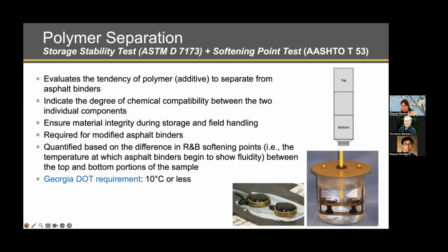So the test is pretty simple. As you can see here on this illustration, we have the blend of the asphalt binder with the polymer or the additive, in this case, graphene. We have the materials stored in a cigar tube, that is an aluminum tube, as you can see in this picture. And after conditioning at cold and room temperatures, we separate the top and the bottom portions of this tube, and we evaluate the properties of the binder on top and bottom. And the property that was measured was the softening point, as you can see here in this picture.